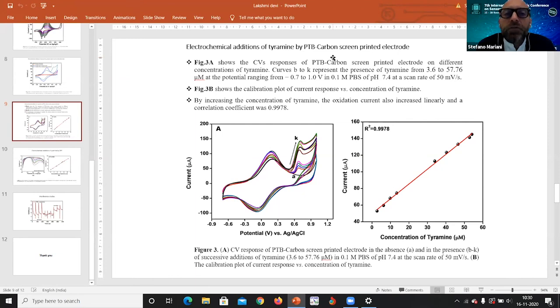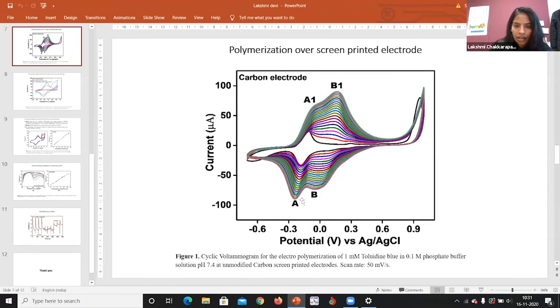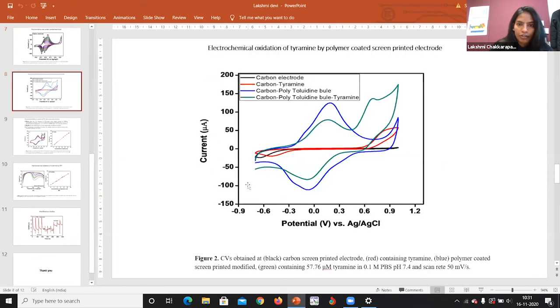Any other questions? I don't see any. Alberto, do you have one? Yes, Stefano, I have one. Yes, please. Your electrodes are printed electrodes. Yes. What about the stability of your electrodes? Stability after the polymerization, we run cyclic voltammetry for 100 cycles, because here you could see the current of polymerization is somehow 100 microamperes. But when we took this electrode and analyzed with tyramine, you could see the same current, nearly 100 microamperes.